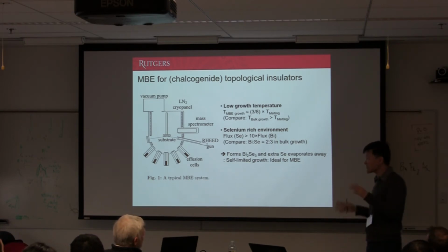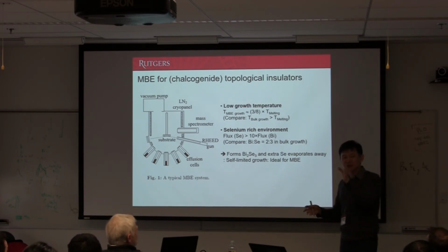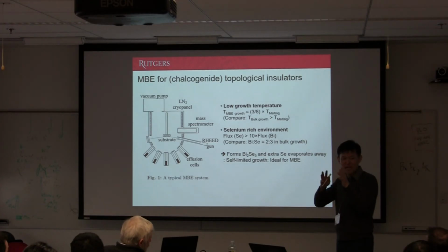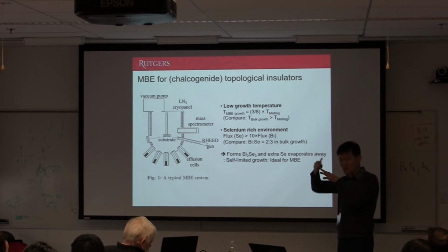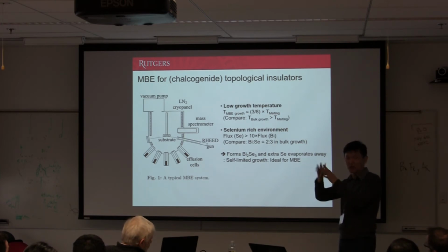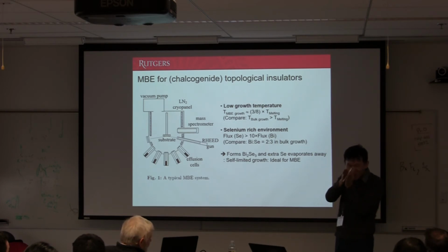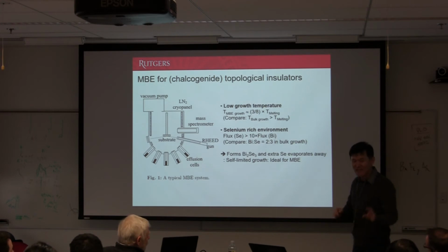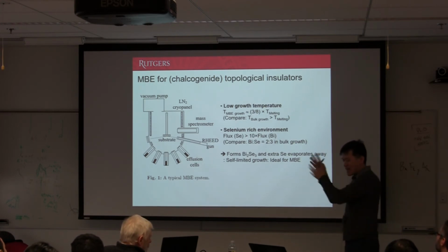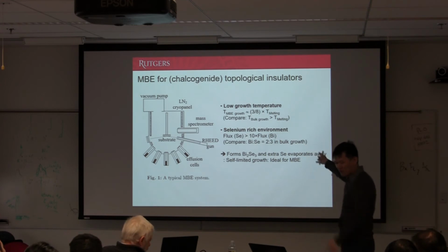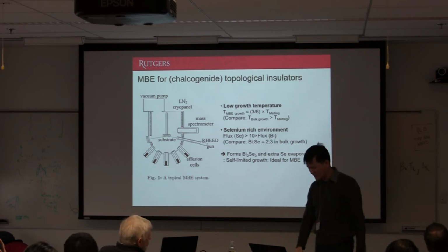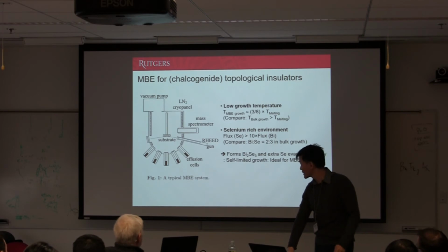But sometimes in certain cases, people want to. A good example is if you want to grow Fe2O3 versus Fe3O4. That's very tricky, because in some sense Fe2O3 may be a little bit easier, since Fe2O3 can be grown at the most oxygen-rich condition. But if you want to grow Fe3O4, you have to somehow go to that small window. It's very tricky. But if you are on a line compound, on the very far right or far left, then MBE is very easy and perfect.